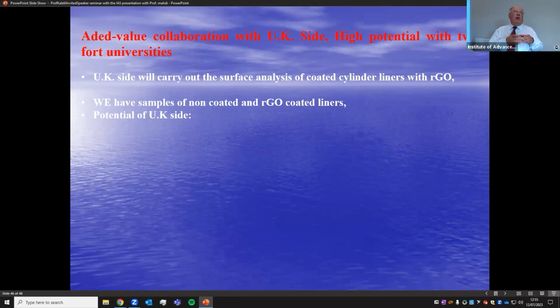We also polished the hone surface because the coating can be done better on it; the machining marks make it a bit difficult. We succeeded, but I also have non-coated samples, just to start. So your potential is here. First of all, I would like to ask if it is possible. The coating thickness is important for us to see for my samples. If we learn the coating thickness according to the coating time, then we can progress better.